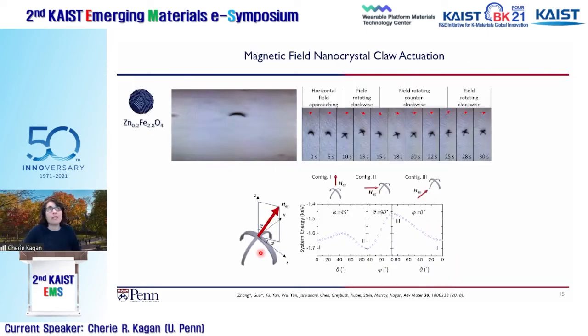We could also do this with magnetic materials, just to give you a sense that this is broadly possible. This is a structure here where we made a claw, and then we came with a magnet, and as we rotated the magnet, the structure would change in response to the magnetic field, and we could drive its orientation as it was suspended in the solvent. It's a little bit easier to see here in a handful of snapshots that we took. The reason, which we studied and modeled, is that in this sort of curved structure, there's one low energy axis. And what that means is that as we control the magnetic field, as it bisects the arms, we're actually turning the whole claw structure.